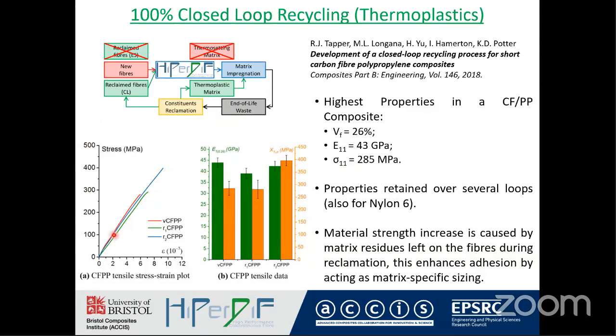And as you can see, the stress against strain behavior for the virgin carbon fiber polypropylene, the recycled carbon fiber polypropylene, and a second recycled step demonstrates that we're still able to maintain properties, and indeed on the second recycling, we actually get improvements in the strength, which we believe is due to residues of matrix on the fibers, as shown by microscopy, which tend to then act as a matrix-specific sizing. And we've achieved the highest properties in a carbon fiber polypropylene composite, at a fiber volume fraction of 26%, to get a modulus of 43 gigapascals and a tensile strength of 285 megapascals.